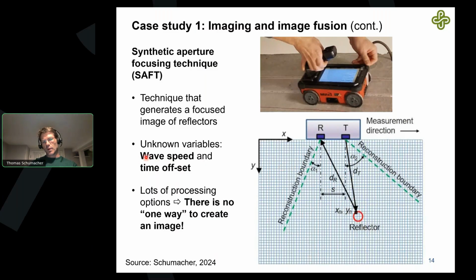The cool thing is that once we have wave speed, that tells us a lot about the material. In the case of ultrasound, if you have a very stiff concrete, the wave velocity will be very high. If we have a not so stiff, low strength concrete, the wave velocity will be low. So there are some additional things we can learn. There's a lot of processing that goes into this, and I want to stress there's no one way to create such an image. There are many things that can be done to enhance the image, so one image done by one person might look different than an image done by another person.